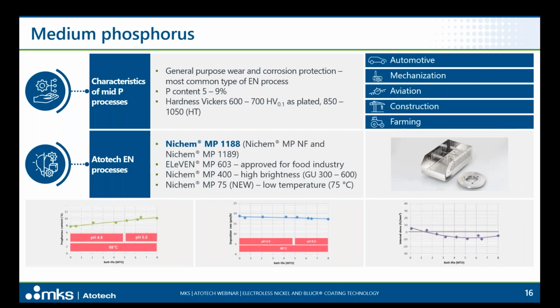In the range of medium phosphorus electroless nickel, which is the most popular electroless nickel technology on the market, these processes are used for general purposes regarding wear and corrosion protection. They have a phosphorus content of 5 to 9. The as-plated hardness is about 600 to 700, and it can be increased to 850 to 1050 after heat treatment.